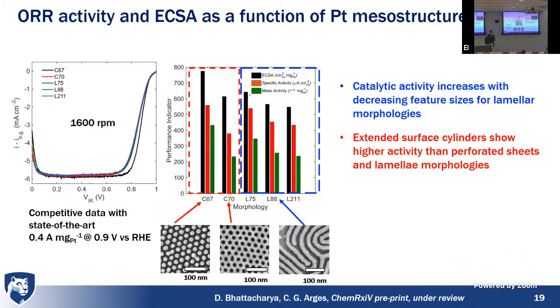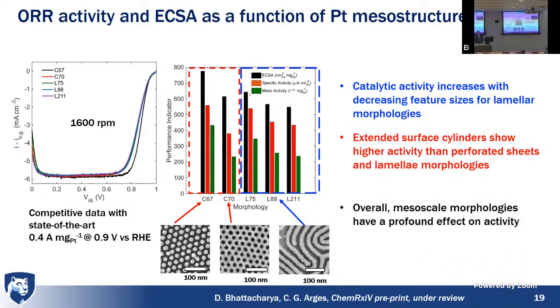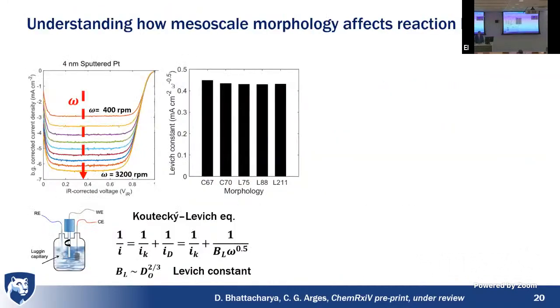We measure the electrochemical surface area using cyclic voltammetry, measuring the hydrogen underpotential deposition. I won't go into the details of that. But what we're seeing here is that morphology has a profound impact. Control of the morphology at the mesoscale has a profound impact on electrocatalytic activity, right? And I showed you earlier that even when you make fancy nanoparticles, if you can't control the mesoscale morphology, it can be difficult to infer how that nanoparticle structure is affecting electrode performance.